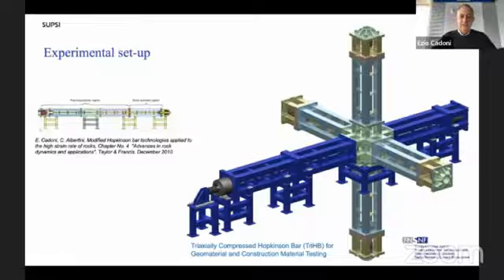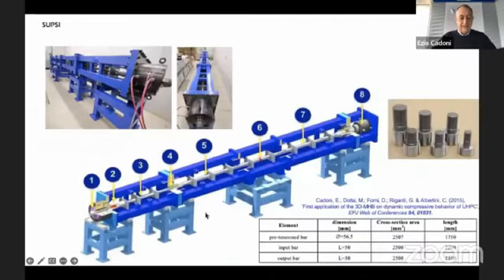The input bar is the solid continuation of the pretension bar, and the other 5 bars can be considered as the output bars, and at the end of each of these 5 bars there is another hydraulic actuator that permits to impose the triaxial state. All the bars are instrumented with strain gauges in order to record the wave propagation in the system. The results I'm presenting you were obtained by using only the monoaxial configuration, the actual configuration, this one, where the specimen is pre-strained before the dynamic test.